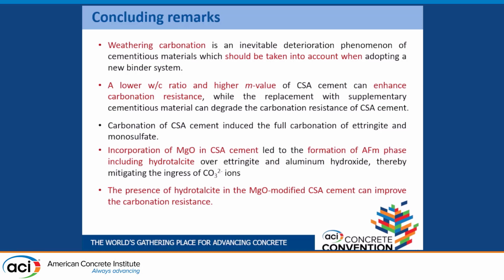So as I said, weathering carbonation is an inevitable deterioration phenomenon of cementitious materials, which should be seriously taken into account. Also, a lower water-cement ratio and higher M value of CSA cement may enhance carbonation resistance. And carbonation of CSA cement induces the full carbonation of ettringite and monosulfate. And incorporation of magnesium oxide in CSA cement led to the formation of mainly hydrotalcite over ettringite, thereby mitigating CO2 ingress. Finally, the presence of hydrotalcite in the magnesium oxide modified CSA cement can improve the carbonation resistance.